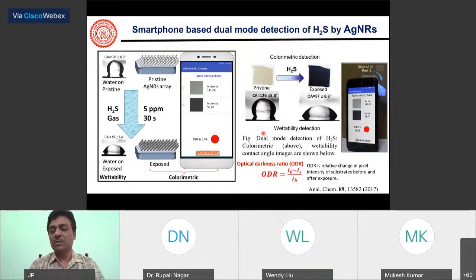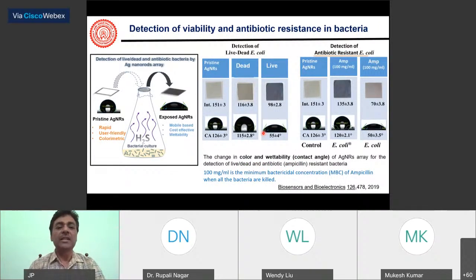And finally, you can see here that if the bacteria is dead, there is only a very small amount of H2S detected, so from the change in color we can figure it out, and also from the contact angle, where you can see a huge change.